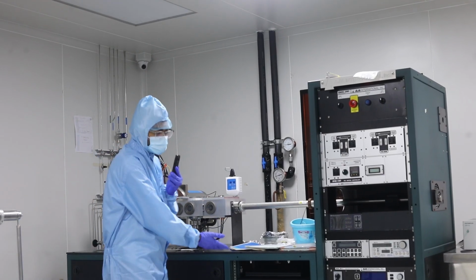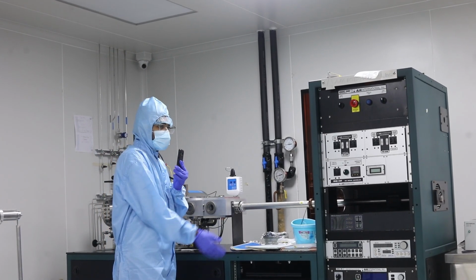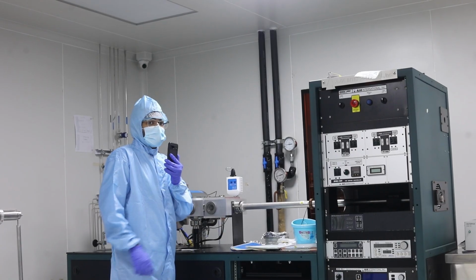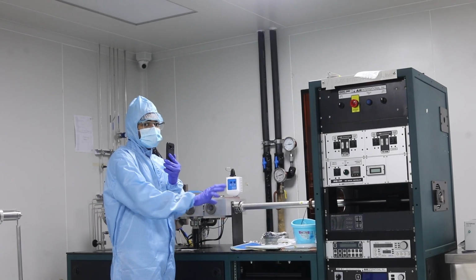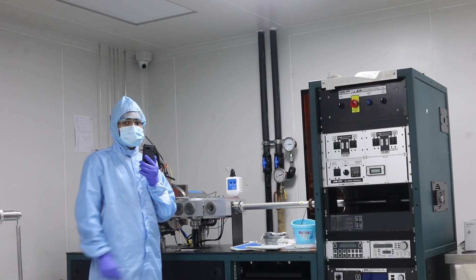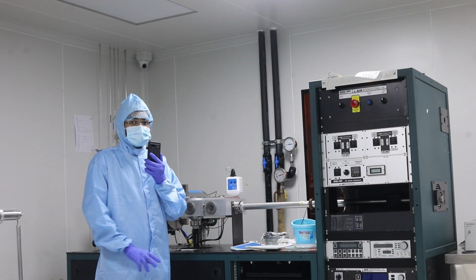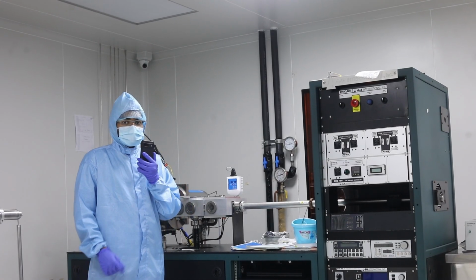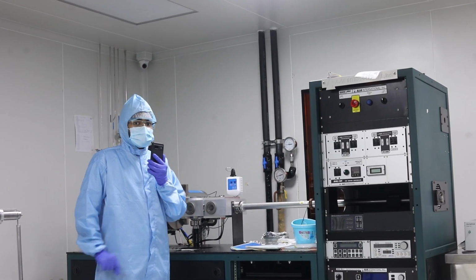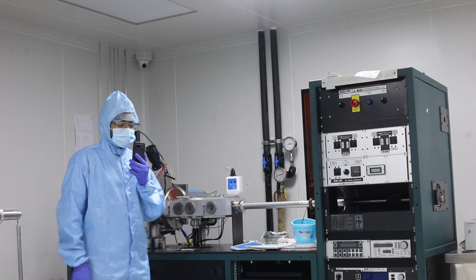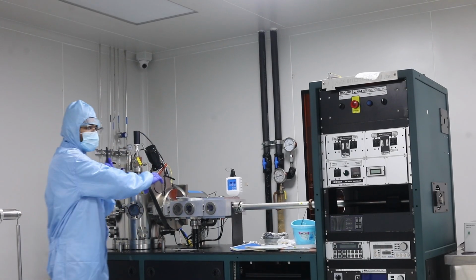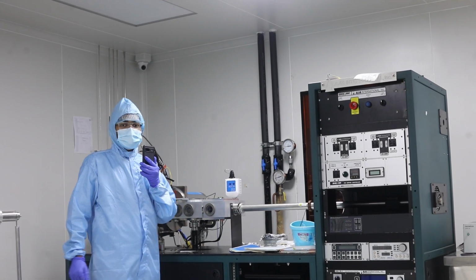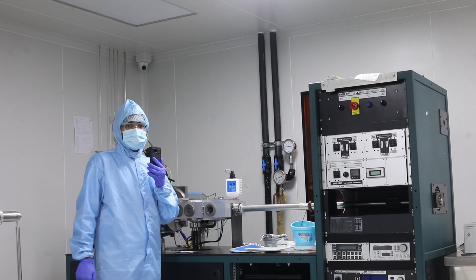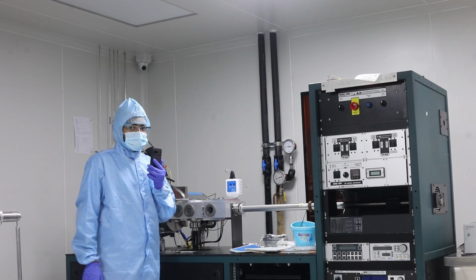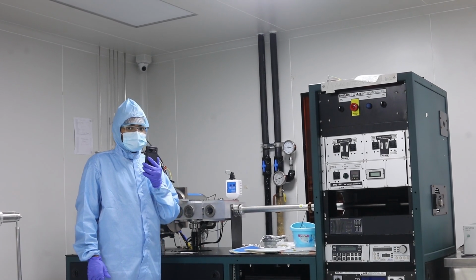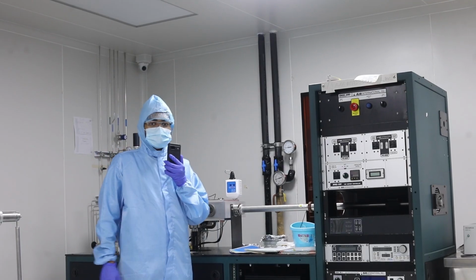We also have some digital systems which control the whole process. We can see how much time is remaining. Generally, we put 800 seconds for 80 nanometers of sample sputtering. And we also have a cryogenic vacuum pump which generates a very high vacuum of a magnitude of 10 power minus 9 torr. This is about sputtering.